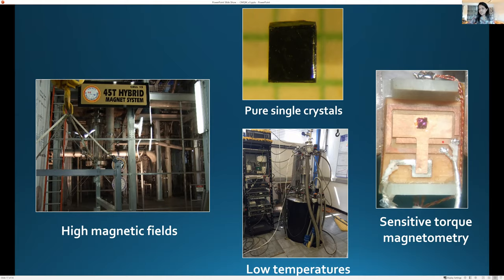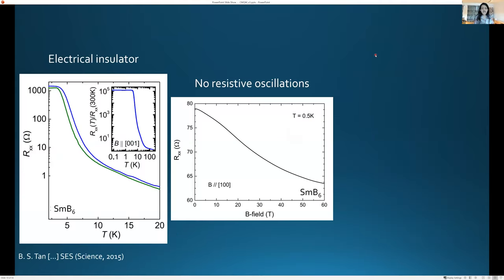So this is an extremely sensitive measurement, but it is well designed not to pick up any of the vibrations of high magnetic fields, which is why we can pick up very sensitive quantum oscillations. Okay, so the first thing we look for is resistive oscillations.